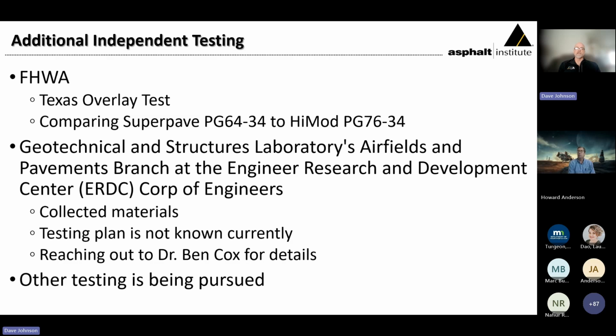We have some additional independent testing. The mobile testing lab for the Federal Highway Administration was in Wyoming doing a project, and so we delivered some of the 64-34 Superpave binder as well as highly modified binder. This material is currently getting tested under the Texas overlay test. I haven't seen any of those results yet, but we should see them soon.